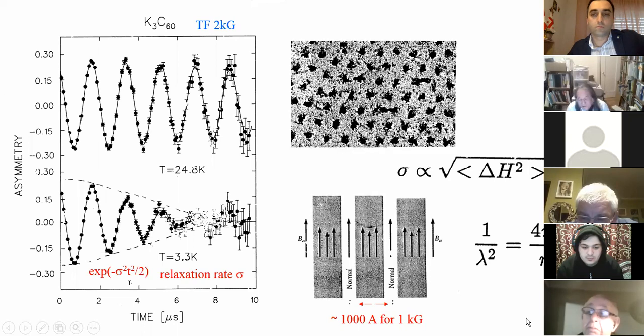And in some mid-1920s or 30s or something, the researcher named Fritz London in UK found out with something called London equation that this 1 over the penetration depth square is related to the superconducting carrier density NS divided by the effective mass. And this is actually the effect that superconducting current flows around this vortex core and then screen the external magnetic field. And this NS over M star is a kind of measure of the superconducting current density.